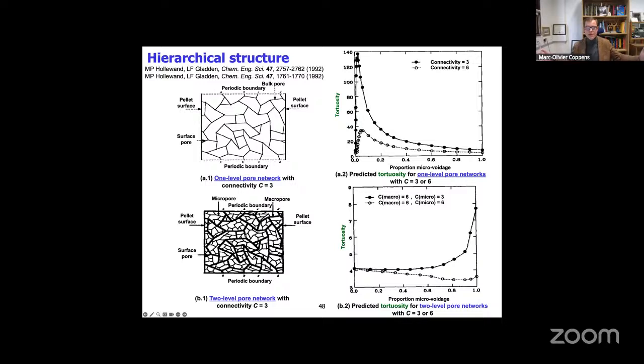You may have a pellet that consists of particles, so with macropores in between, and then you have the mesopores, or you have micropores, even if it's a zeolite, say, inside these crystals, inside the pores. And so it's really important to include these two levels. You can't just discard that, or you get totally unrealistic levels. And so again, what she showed here is an effect on these tortuosities, getting much more realistic results, and also demonstrating the importance again of the connectivity in these materials.